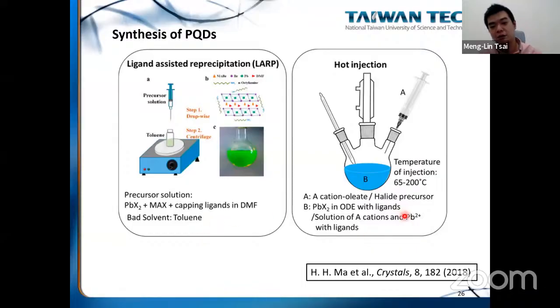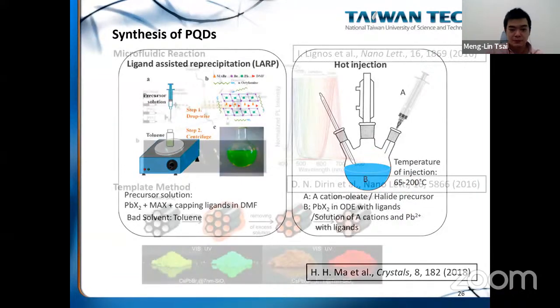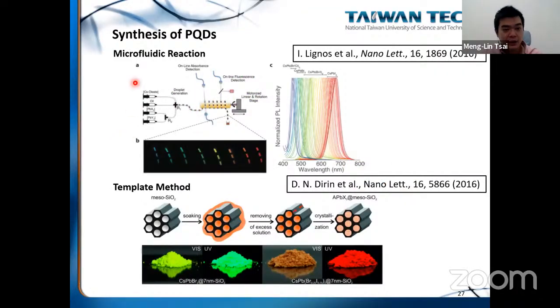Another way is called the hot injection process. You prepare some precursors, and under high temperature, you inject them into a solvent. Under this temperature, the nanocrystals or quantum dots will form in the solvent. And people have also come up with microfluidic reactions to precisely control the emission wavelengths of the perovskite quantum dots.